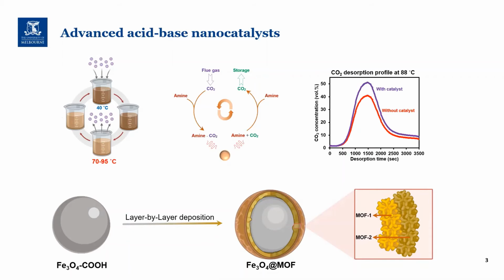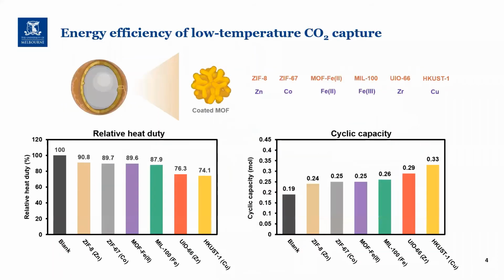Here at the University of Melbourne, we have used a layer-by-layer technique for the self-assembly of different metal organic frameworks on the external surface of acidic Fe3O4 nanoparticles with superior texture properties and catalytic efficiencies. In this project, we coated 6 different metal organic frameworks with zinc, cobalt, iron, zirconium, and copper metal ions and succeeded to significantly reduce the required regeneration temperature to 88 degrees Celsius.